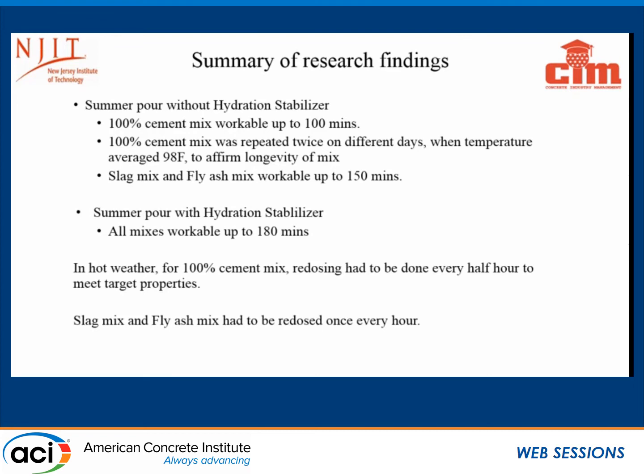I've got a question. Sure. This was a 6,000 PSI mix, correct? Mm-hmm. So it was already mixed with a slump that was being retained through superplasticizers to begin with? Yes. Okay. So we're seeing the effects of the plasticizer. Well, naturally. The lifespan of Super P is about 45 minutes, give or take, optimally. Chemical slump, water slump.